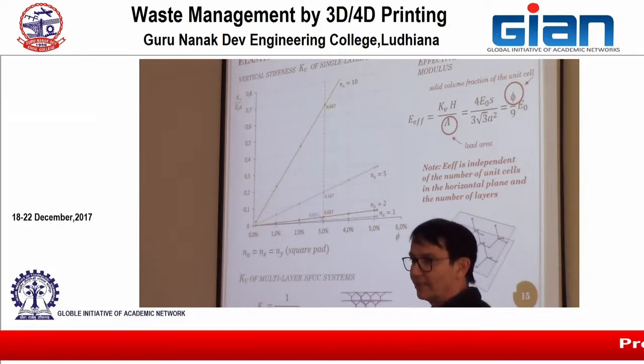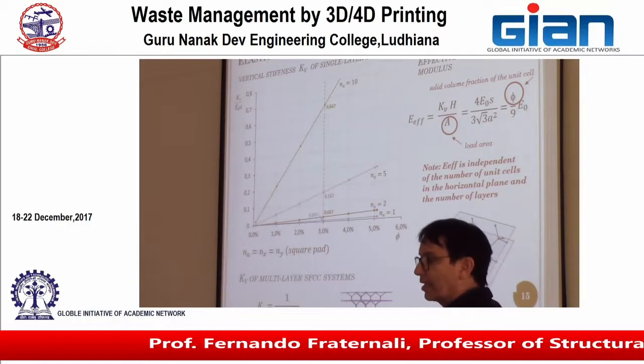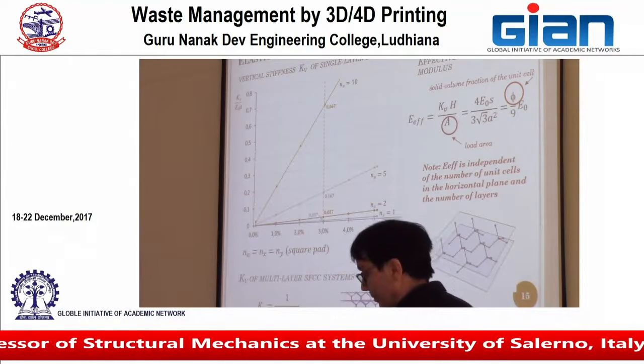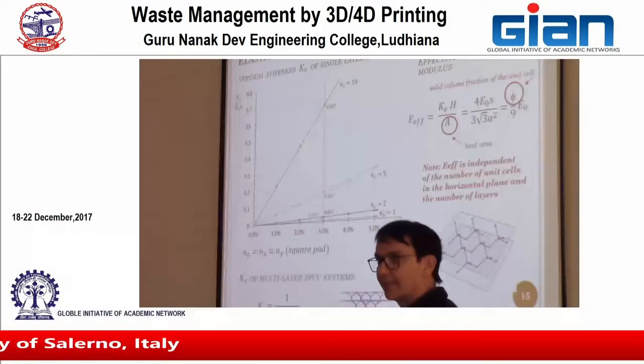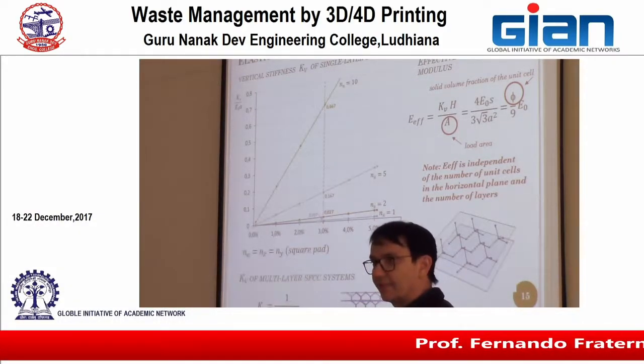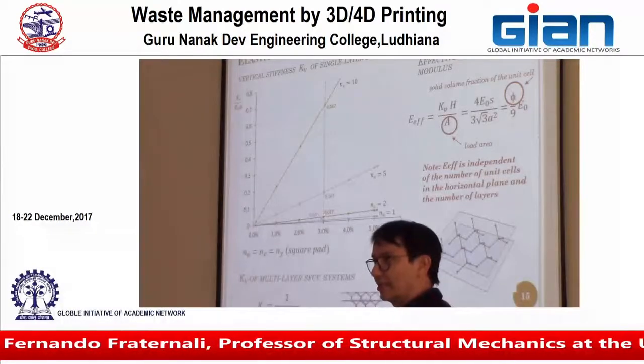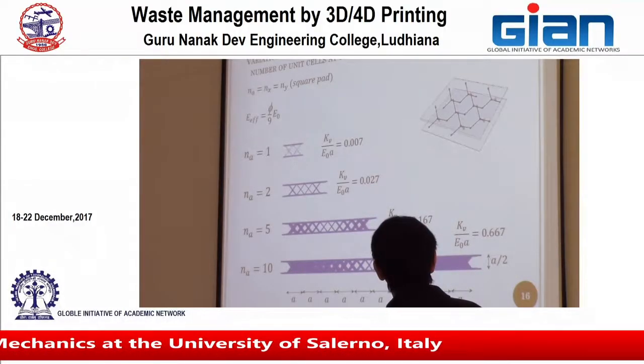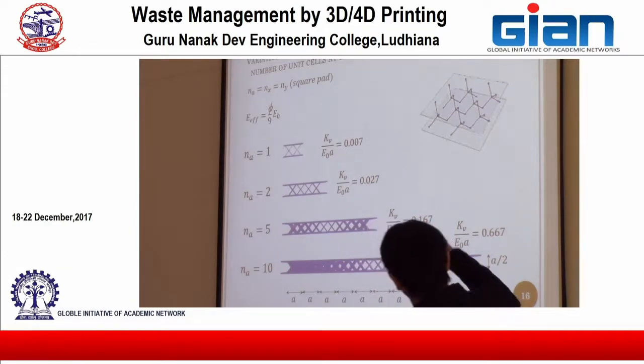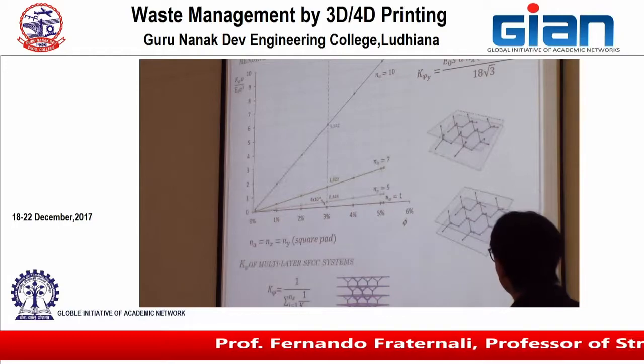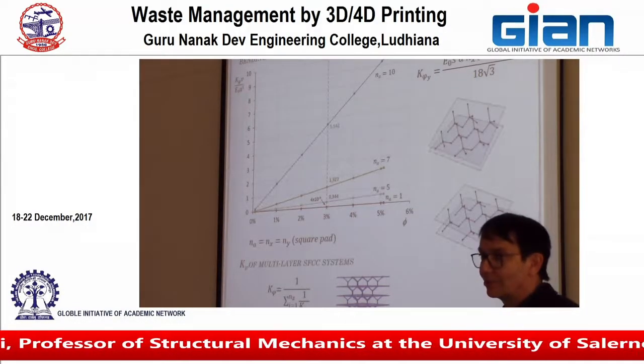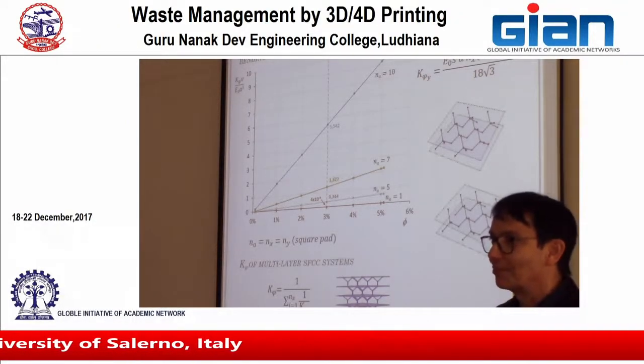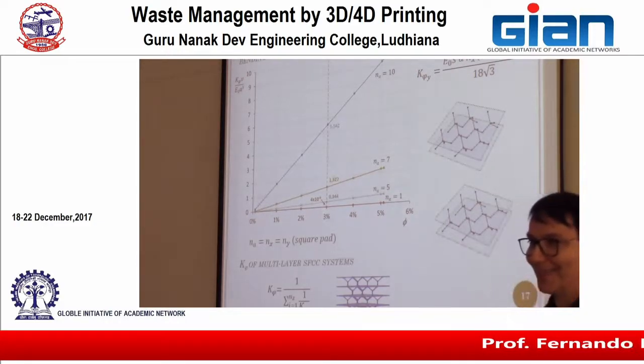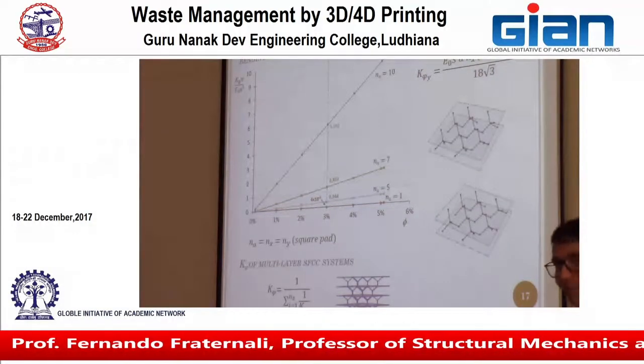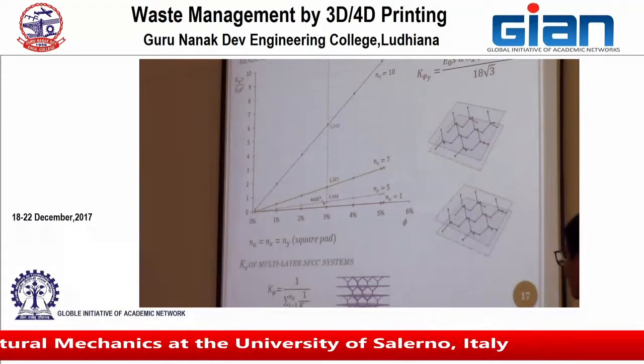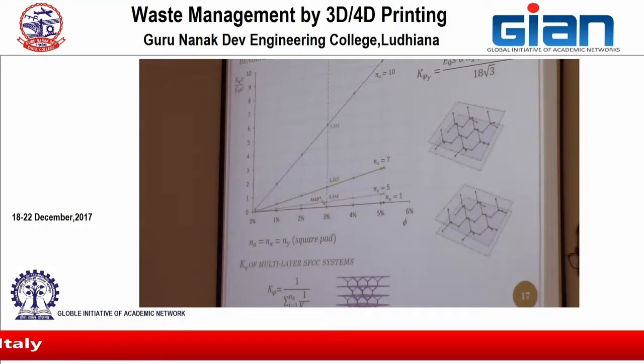So it's really a good candidate to be a seismic isolator because it has considerably high vertical stiffness and considerably low, theoretically zero, horizontal stiffness. It also opposes stiffness to vertical relative motions, and it opposes stiffness also to bending motions. This is what you want, because otherwise the structure will collapse under vertical loadings. You don't want that, you know? So there can be bending moments due to the non-uniform loads in the building. So this was actually a metamaterial good for seismic applications.